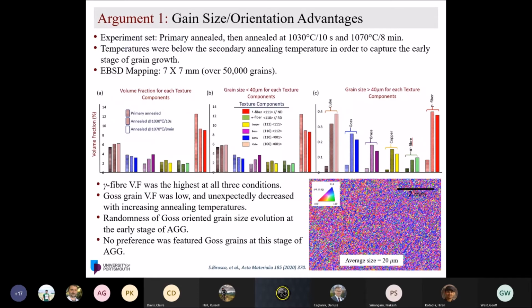We try to validate the theory, and we did a set of experiments for the past 4 years with Ali Nadoum and Dwayne Hawizi. The first argument: we will try to understand if Goss grain actually has a preference or size or orientation advantages, as much of the literature blames that they have grain size and orientation advantages, and we try to understand if they have this privilege during the early stage of normal grain growth.